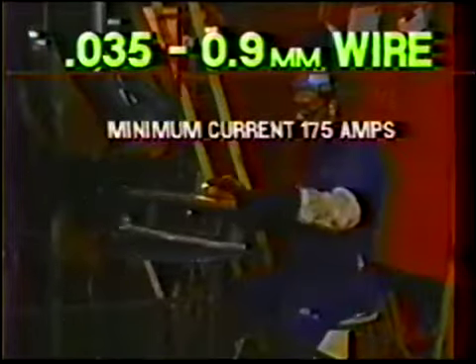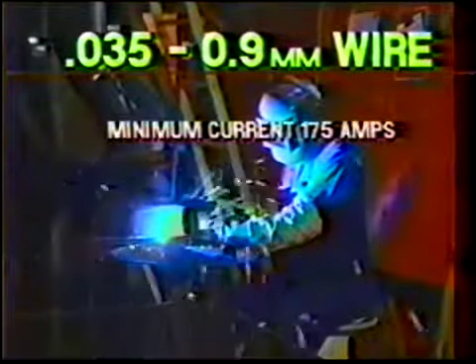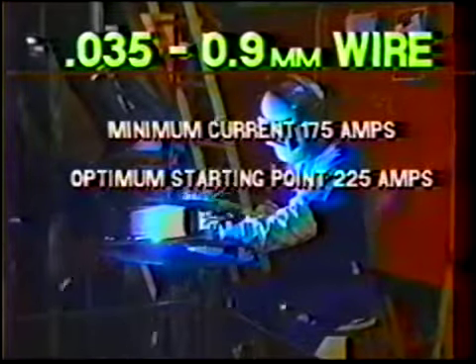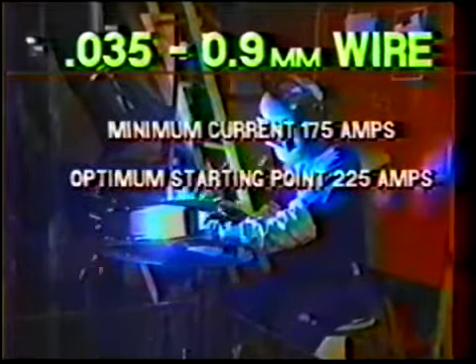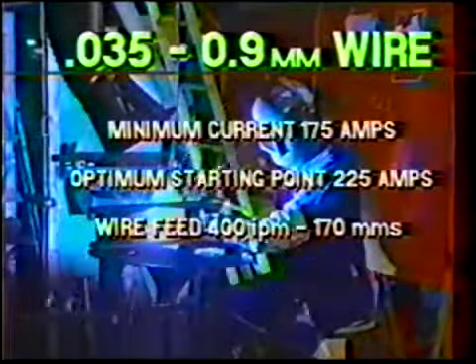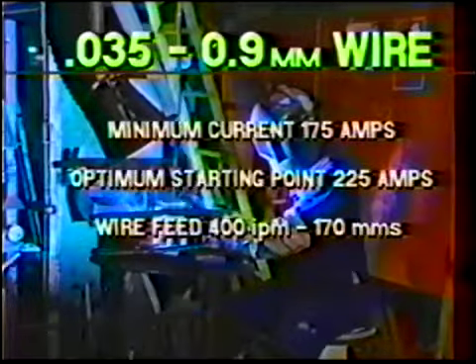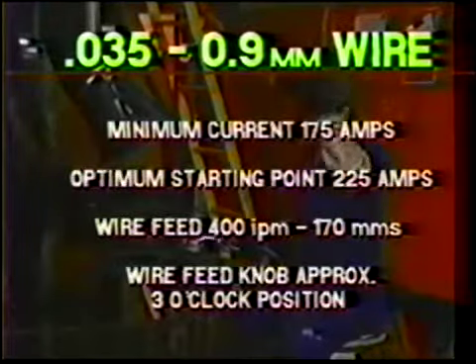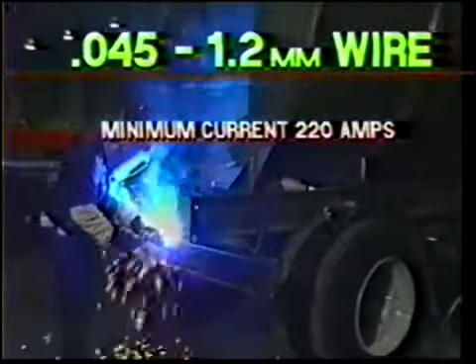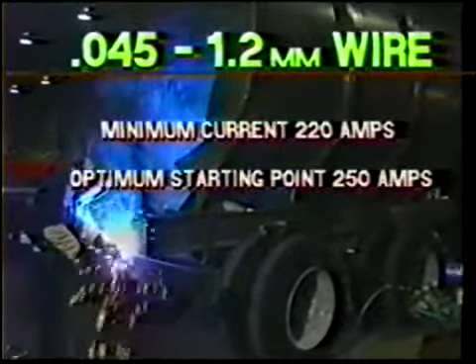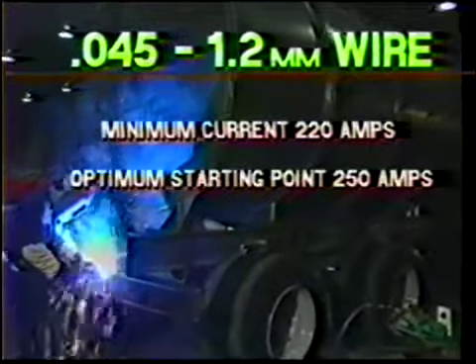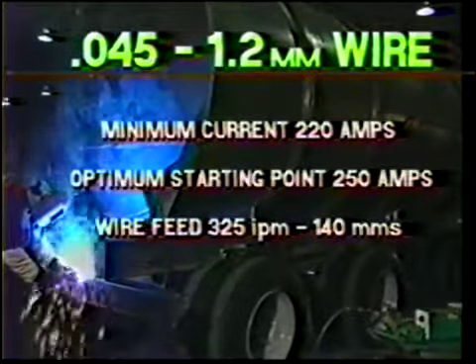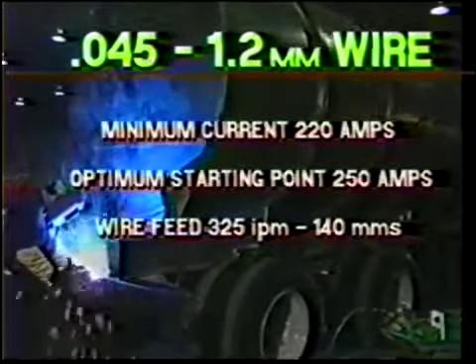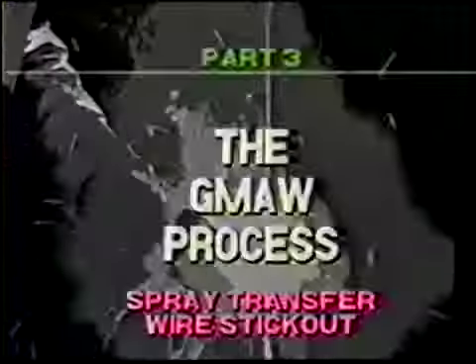For 035 wire, a minimum of 175 amps is required. The optimum starting point would be 225 amps. To obtain 225 amps, set your wire feed speed at approximately 400 inches per minute, or the 3 o'clock position. For 045 wire size, the minimum current required for spray transfer is 220 amps. An optimum starting point would be 250 amps. To achieve this, set the wire feed speed at approximately 325 inches per minute, or the wire feed knob at the 2 to 3 o'clock position.